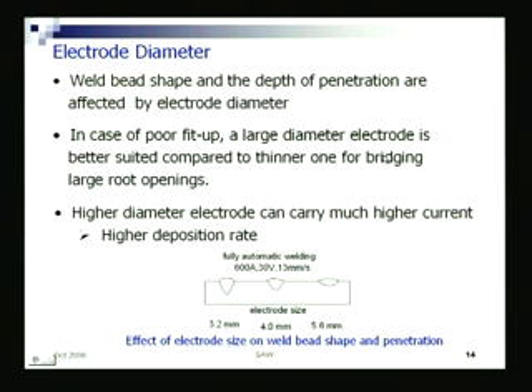Electrode diameter: here in high deposition welding, one can use a much higher diameter electrode, as you can see, you can go even up to 5.6 millimeter diameter, a thicker electrode, so you can deposit much more metal. So the weld bead shape and depth of penetration are affected by the electrode diameter used. A higher diameter electrode can carry much higher current, thereby giving a high deposition rate.